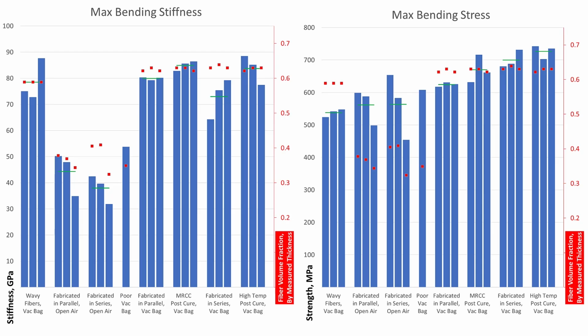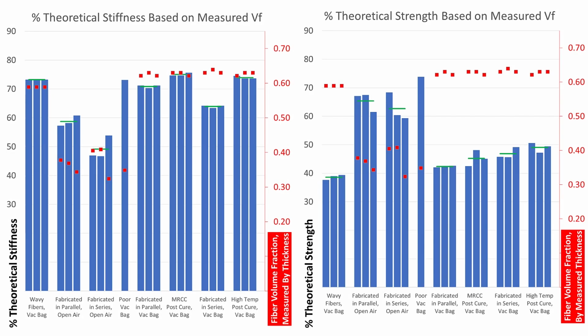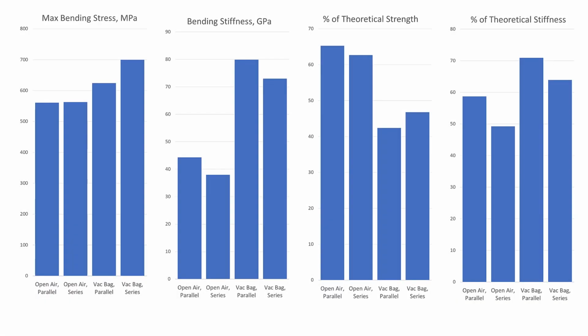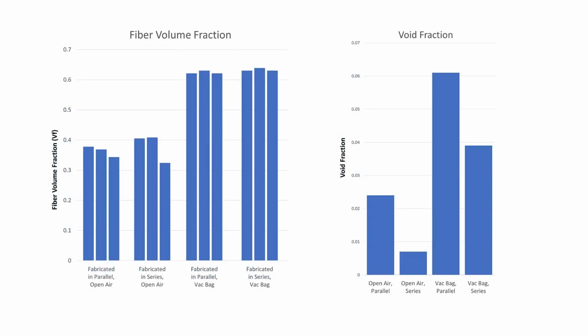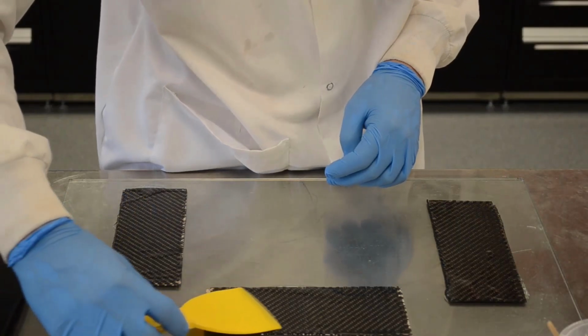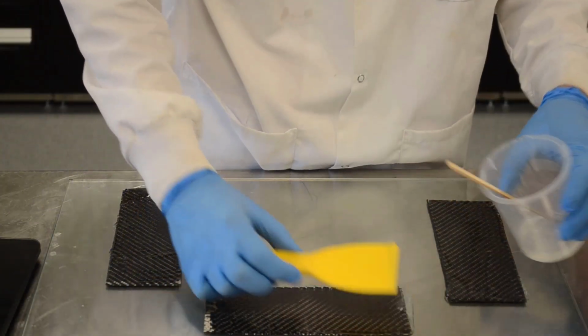Overall, we can observe that higher fiber volume fractions produced by vacuum bagging are associated with superior properties compared to lower volume fractions produced by curing without a vacuum bag. All tested samples had lower properties than predicted based on their volume fraction. It is also notable that there was a difference in properties between the samples which were laid up in series or parallel, which shows that subtly different manufacturing processes can have an effect on part outcomes even if most process parameters seem similar. The value of these tests is that they demonstrate the variability inherent to the wet layup process.